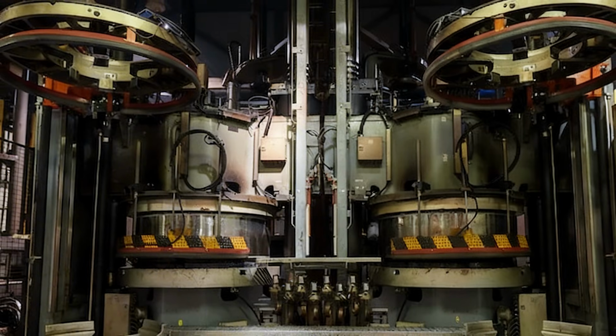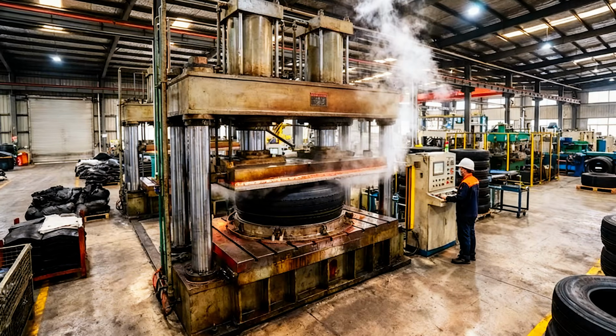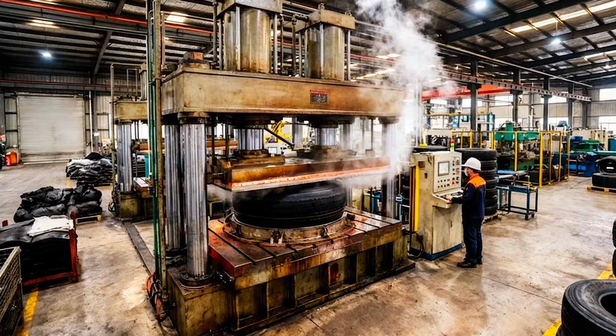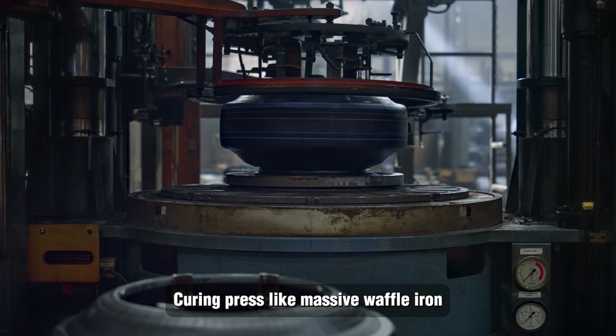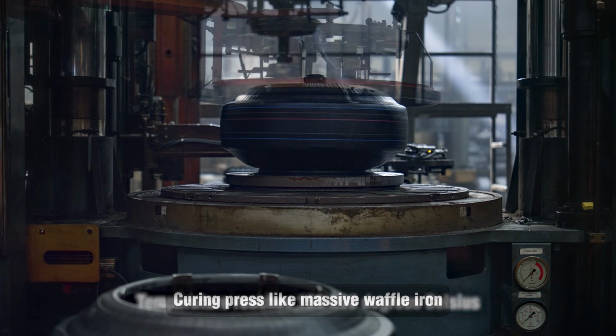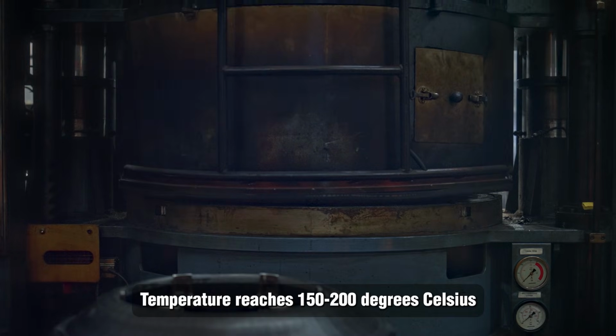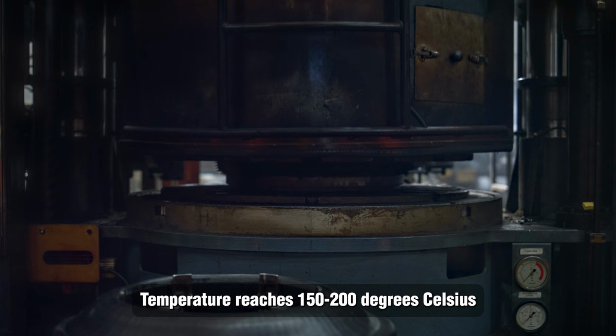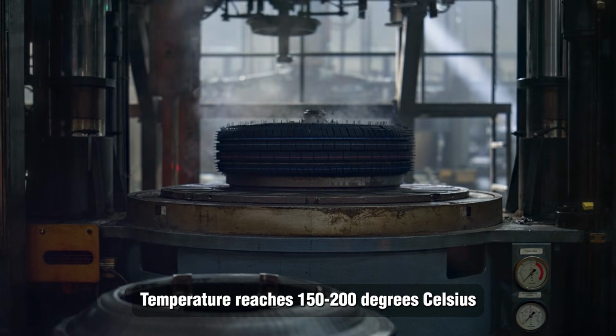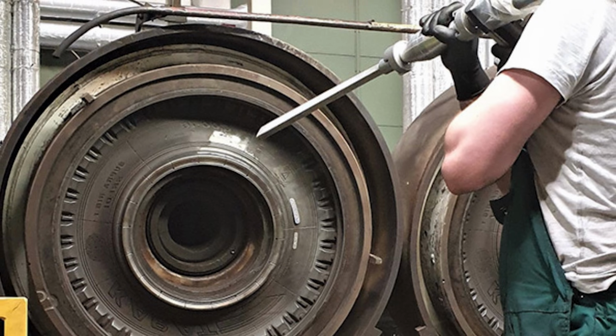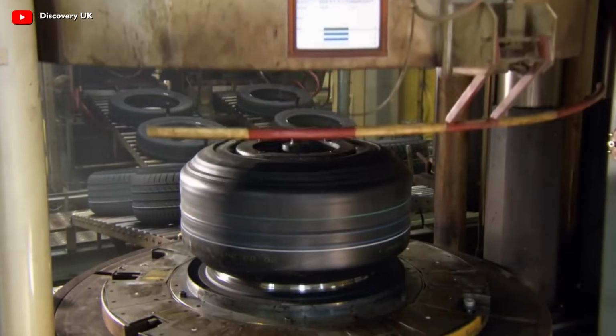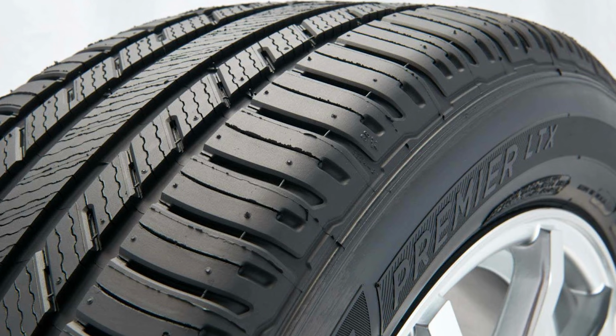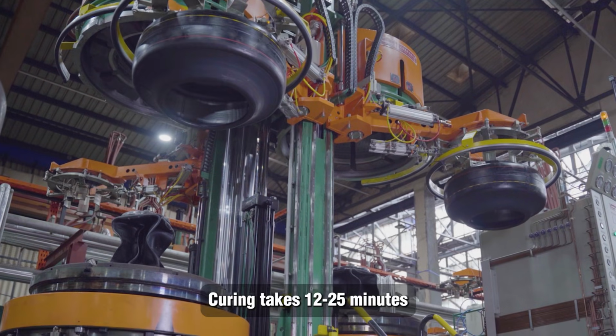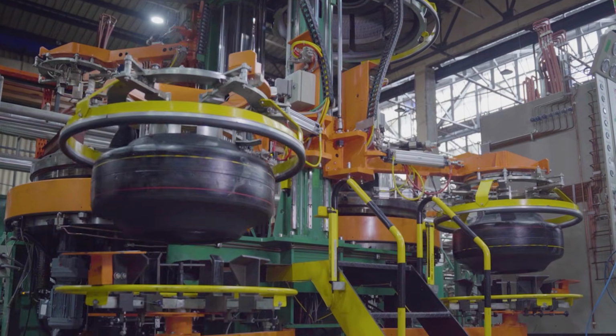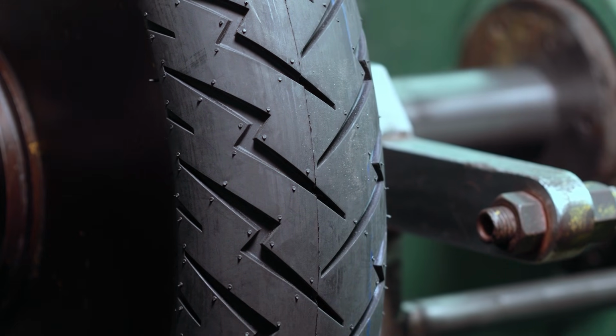Vulcanization represents the most critical step in tire manufacturing, where heat and pressure trigger chemical reactions that permanently cross-link rubber molecules. The green tire gets placed in a curing press, essentially a massive waffle iron for tires. The press closes, applying tremendous pressure while injecting steam or hot water to raise the temperature to approximately 150 to 200 degrees Celsius. The inner surface contains a mold with the tire's tread pattern and sidewall markings. As the rubber heats and vulcanizes, it flows into every detail of the mold, creating the familiar tread grooves and sidewall lettering. The curing process requires 12 to 25 minutes, during which sulfur creates permanent crosslinks that transform soft rubber into the elastic, durable material we recognize as tires.